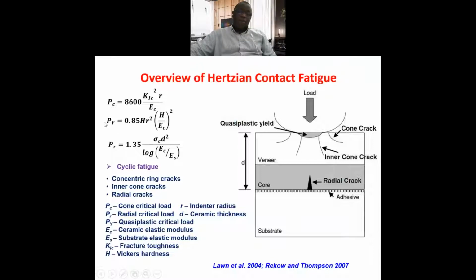The critical load for the quasi-plastic is a function of the hardness, the radius of the indenter, and the ceramic modulus. For the radial crack, it's a function of the maximum stress and the ratio of the moduli of ceramic and substrate. So this one can represent the configuration of our enamel dental system.